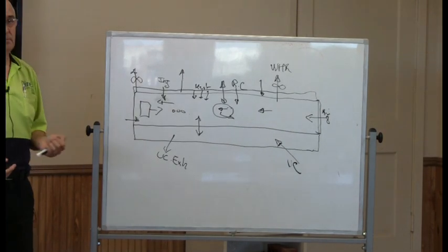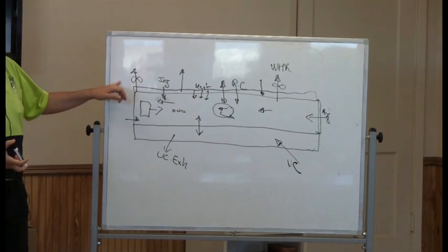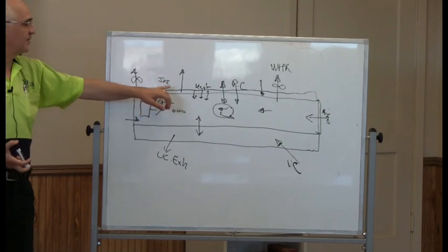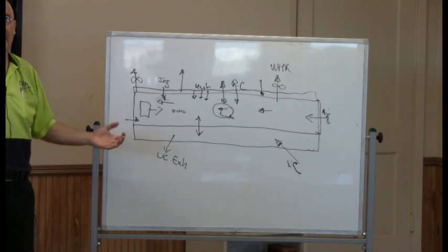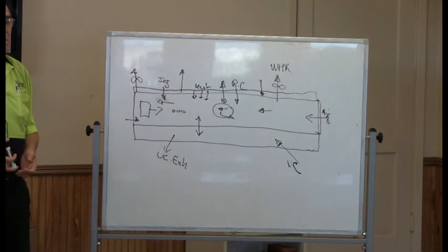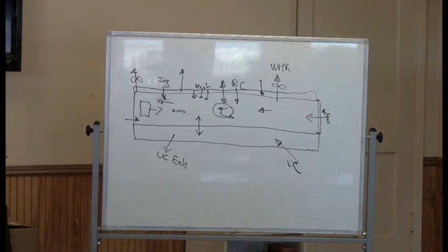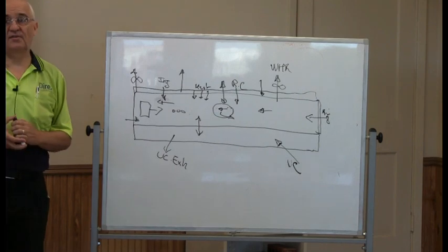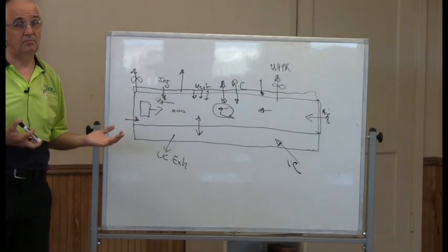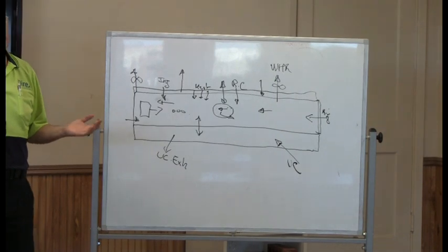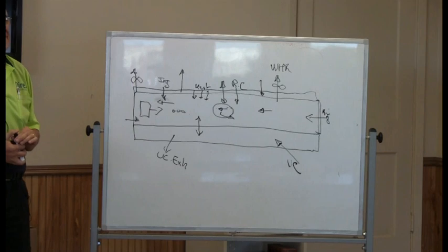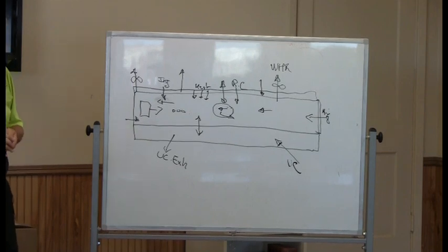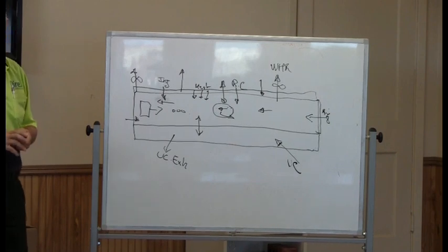The concept of the injection is really to stir. It helps also dilute the smoke. It minimizes the speed of the top air, which is the hottest one. For me, recirculations are more efficient than injection, but it's not the same cost. It's not the same investment. Anything else?